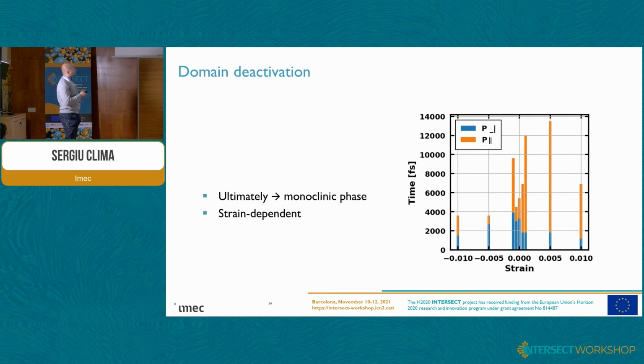Well, we also did some strain simulations on these rotations. So we start with the polarization perpendicular to the surface, shown in blue. And then if we apply tensile strain, it switches rather fast into the parallel to the surface orientation of the polarization, shown with the orange time lines.